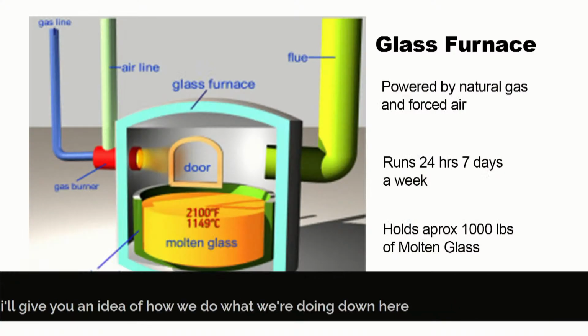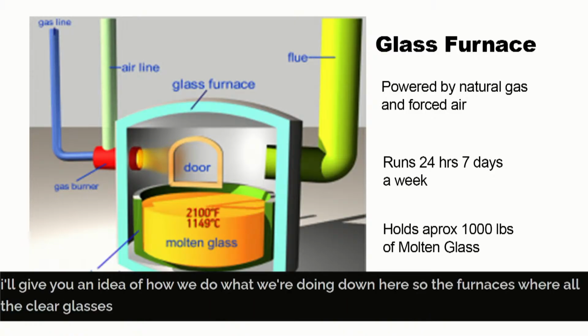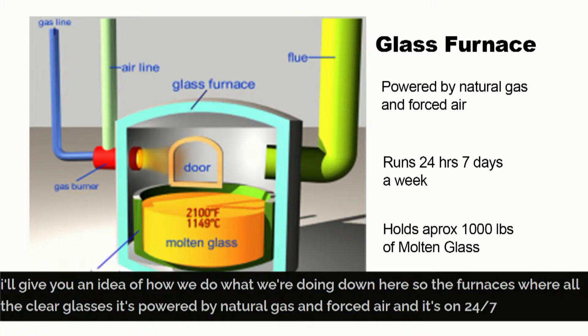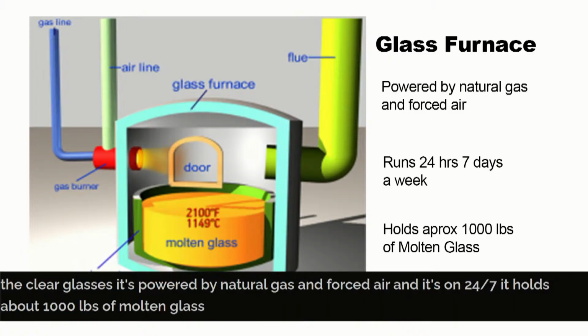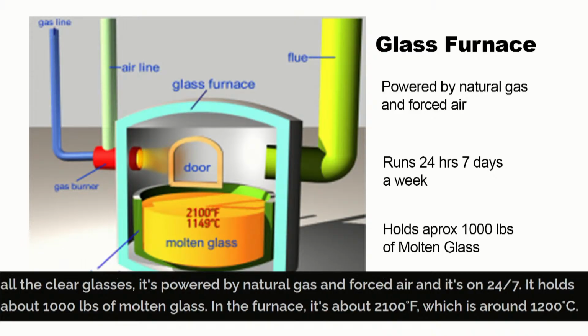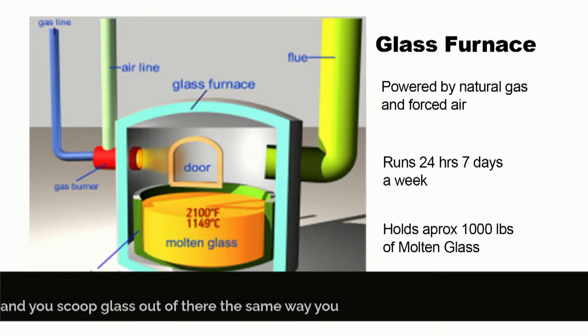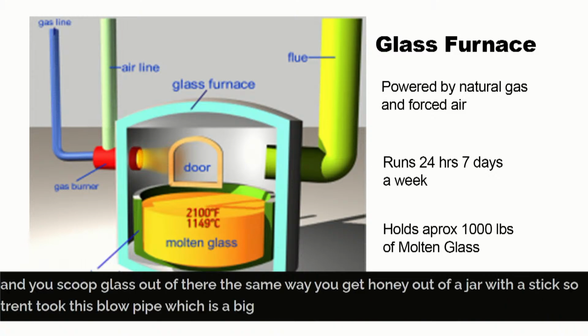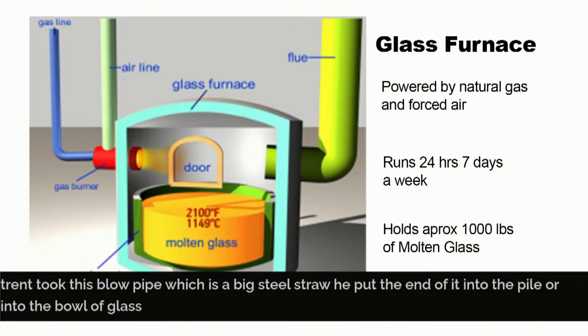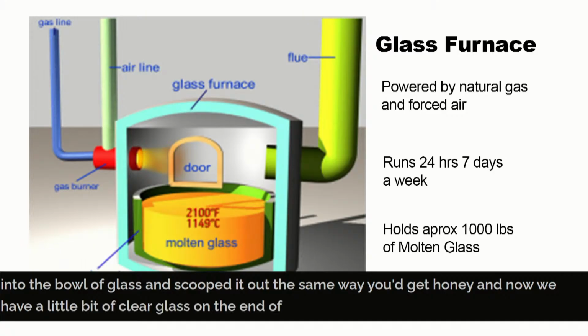So the furnace is where all the clear glass is. It's powered by natural gas and forced air, and it's on 24/7. It holds about 1,000 pounds of molten glass. In the furnace, it's about 2,100 degrees Fahrenheit, which is around 1,200 degrees Celsius. And you scoop glass out of there the same way you get honey out of a jar with a stick. So Trent took this blowpipe, which is a big steel straw. He put the end of it into the pile, or into the bowl of glass, and scooped it out the same way you'd get honey. And now we have a little bit of clear glass on the end of the stick.